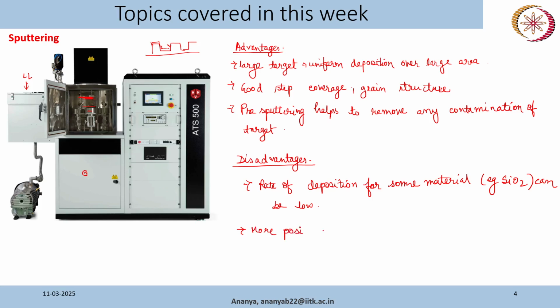If our argon gas is not pure, that will also create problems. Like, if a small amount of oxygen is present in the argon cylinder, that will also change our film property. Basically, there will be some oxygen, some oxides in our film. Okay, this is what we faced once in our lab. The argon was not very pure.